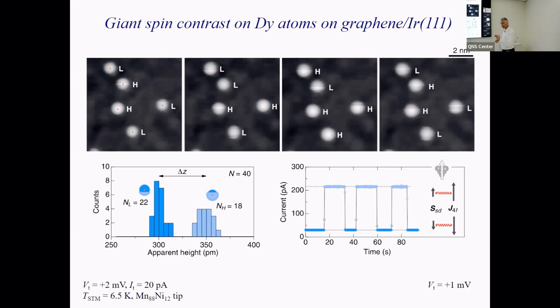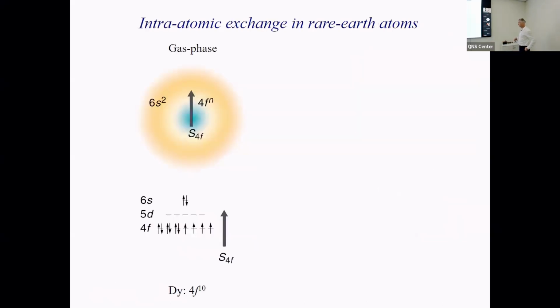So we know now for dysprosium on graphene, these are systems that have a strong polarization in the outer shells. So you can ask yourself whether it's a good idea to describe a system that has a strong polarization in the valence shells by simply a quantum number, which is Jz, or projection of J along the out-of-plane direction, but considering only the 4f electrons. That's what everyone does in molecular magnets, for example. They look into this J that comes from the 4f electrons.